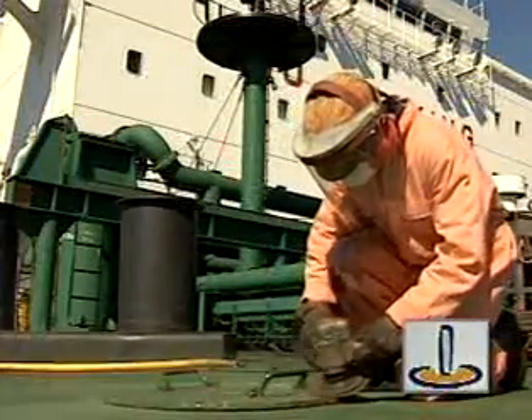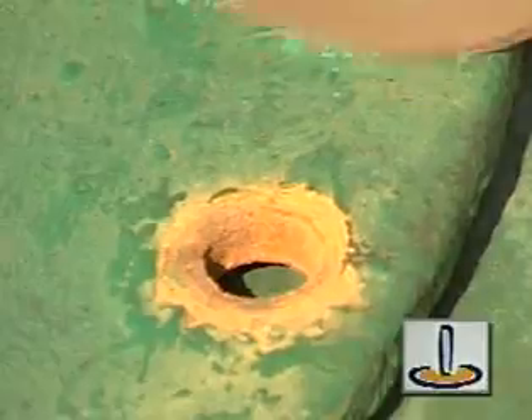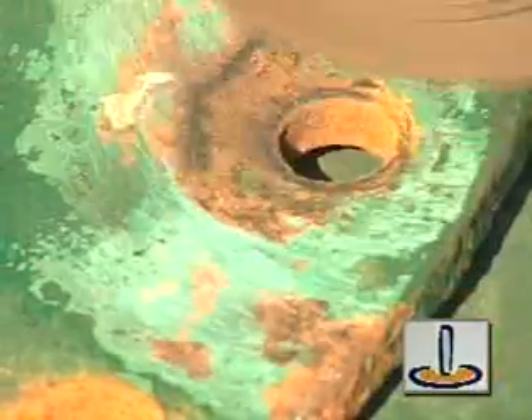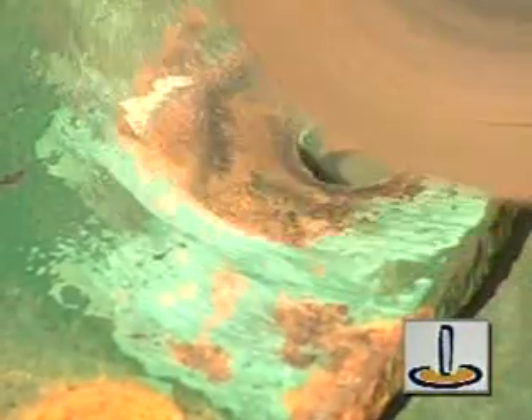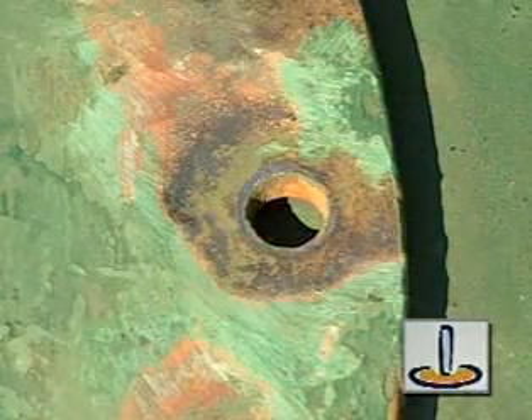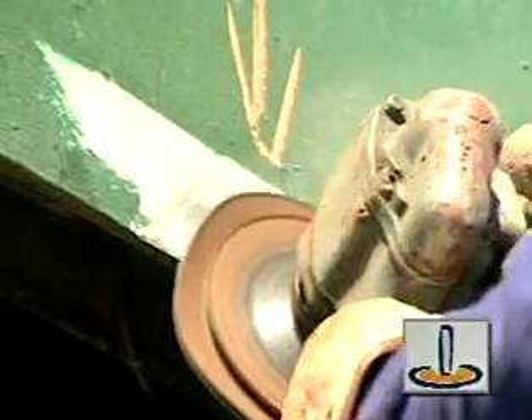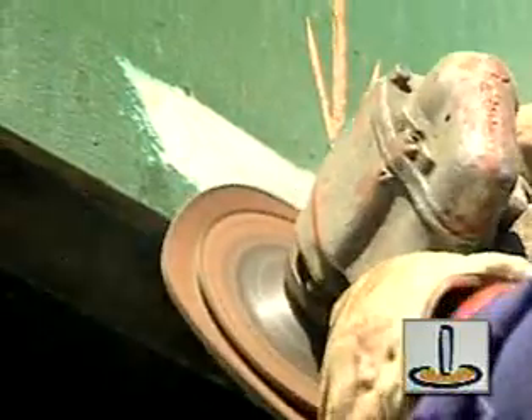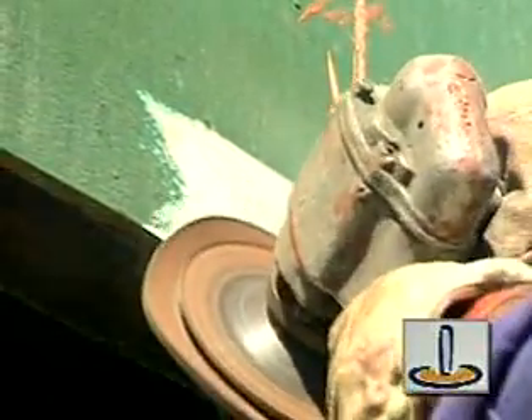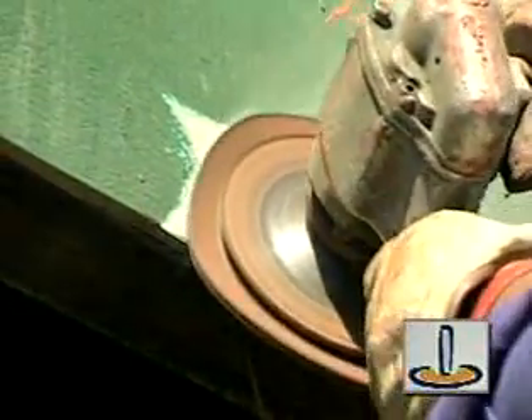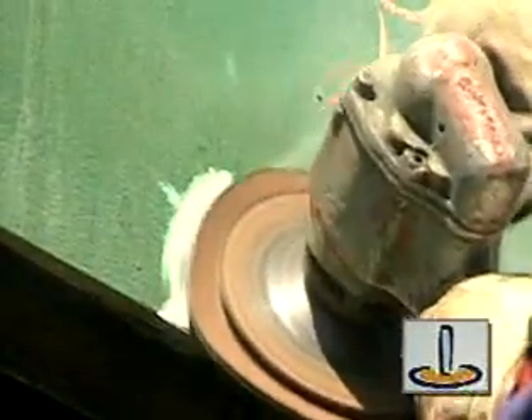The old paint may be several layers deep. By abrading the edges of spot repairs to a distance of about 50 millimeters, an overlap area is created, allowing the freshly applied paint to stick evenly to the prepared spots and the surrounding overlap areas. Paying insufficient attention to feathering will prove costly in the long term, as these areas are likely to be points of poor adhesion and subsequent coating breakdown.